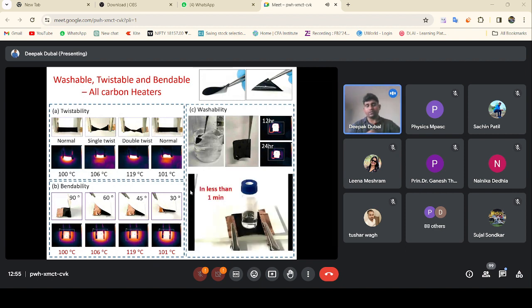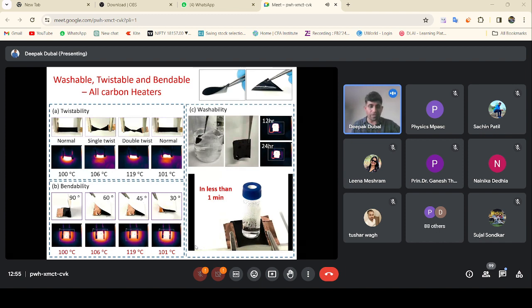But what we learned is, whenever we were testing these heaters with the thermal camera, we could see the temperature was 100 degrees Celsius. But when we actually touched the heater, the temperature was almost normal. So the heater was cold. We were surprised why it was like that. And then we realized it is because the heat is in the form of radiation and not from resistive heaters. You can see we put a very small amount of water on the heater and it actually starts heating it. So what we learned from this is that it is a very, very interesting and very safe technology.